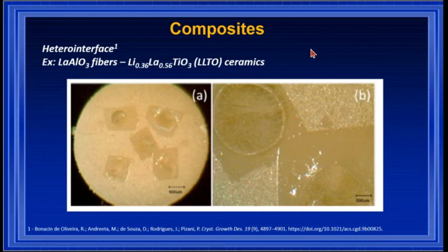Regarding the heterointerface, we studied lanthanum aluminate fibers in a matrix of lithium lanthanum titanate, LLTO for us here. It is well known that it is very hard to produce single crystals of lithium lanthanum titanate. So we try to produce in situ crystals interconnecting the two electrodes, as we said before. We can see here the ceramics with lanthanum aluminate fibers, where we can see very nicely shaped crystals growing on the side of the fibers.